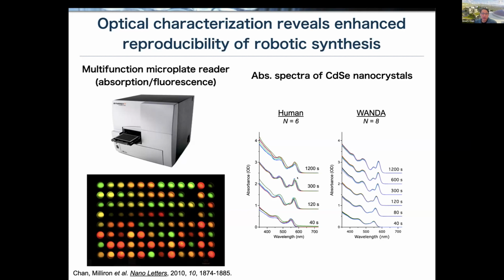So the first thing that we did when we developed Wanda was to try to understand how reproducible it was, because that's a really common problem in nanotechnology, is that many of the reports that you see are difficult to reproduce. So first I had my undergrads make 6 different manual syntheses of cadmium selenide nanocrystals. And you can see that they have this distinctive shape of a cadmium selenide nanocrystal. In particular, they have these peaks that tell you how big the nanoparticles are, and the width can tell you the distribution of sizes.